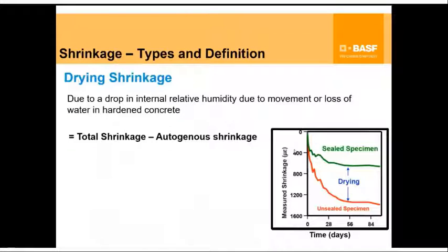Drying shrinkage is the second type of shrinkage. And autogenous shrinkage is also becoming more and more relevant because people are starting to realize it. These kinds of shrinkage happen when you are going to higher grades of concrete, because in this case, your water is low enough that there is no worry about plastic shrinkage cracking. Your bigger problems are chemical and autogenous shrinkage and drying shrinkage. The best way to look at drying shrinkage is to look at a sealed specimen versus an unsealed specimen and measure the differential shrinkage. That's pretty much what drying shrinkage means.